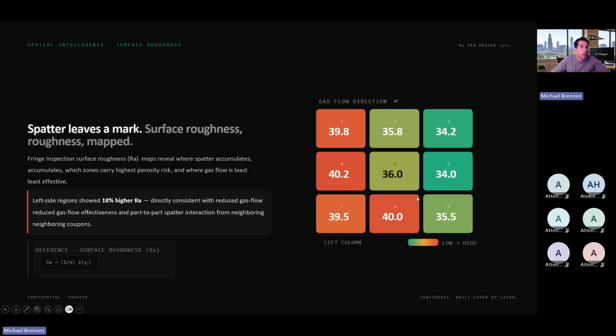The parts with the best surface roughness ended up being parts 3 and 6 when we measured the surface roughness across the entire region of interest. And then the surface roughness continued to get coarser or rougher as we moved to the left and down, again, into the gas flow against our build order. So this continues to be on trend for our hypothesis.